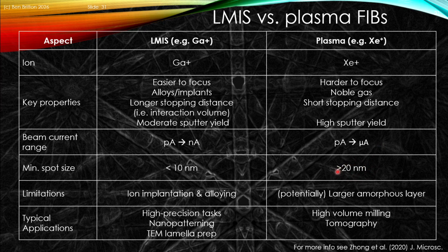We're limited a bit on the ultimate spatial resolution because of the shape of the probe. They're slightly different depending on your manufacturer. Those resolutions can vary. If you're not careful because of how this beam stops, you can get a relatively large amorphous layer, but there are ways to reduce the amorphous layer, the damage of that surface, but we don't have things like ion implantation or alloying really to worry about in here.